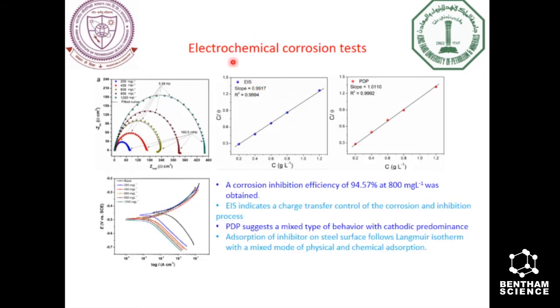First of all, the electrochemical corrosion tests were undertaken, in which we observed that the inhibition efficiency rose with the inhibitor concentration, and a high efficiency of 94.57% was obtained at an inhibitor dose of 800 mg per liter. And a charge transfer control of the corrosion and inhibition process was obtained. In the potentiodynamic polarization studies, we obtained that the corrosion currents decrease with the continuous addition of corrosion inhibitor, and a mixed type behavior with cathodic predominance was observed.